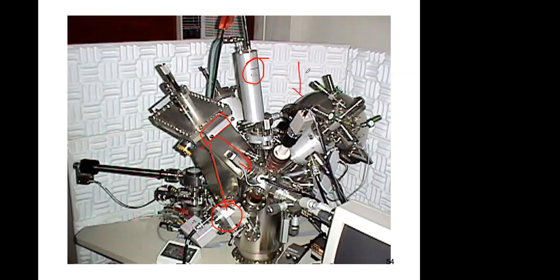Back here is the hemispherical analyzer. This area here is the ion gun, so it has different gases. It has helium, argon, and also oxygen. Oxygen is used also for SIMS to enhance some sputtering yields. You can use helium to do ion scattering spectroscopy, and argon to do sputtering, just to remove the surface. That's why you have several gases in this system. And back here is a mass spectrometer, so you can do mass spectrometry. And here is where you put your sample.